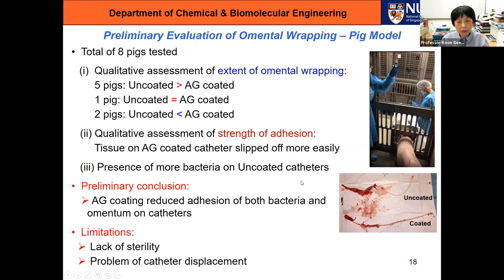And the presence of bacteria is not surprising because this pig really stays in a very unhygienic place. It will just lie around near its droppings and so on. So bacteria migrating into the catheter is not surprising. So our preliminary conclusion is that the agarose coating looks like it is possible to reduce both bacteria and omental adhesion on catheters. But we know that this experiment really has some limitations.